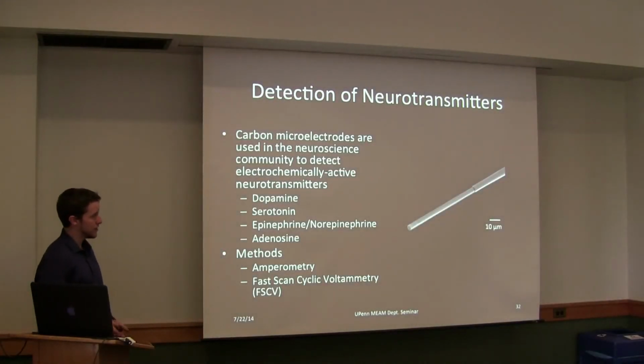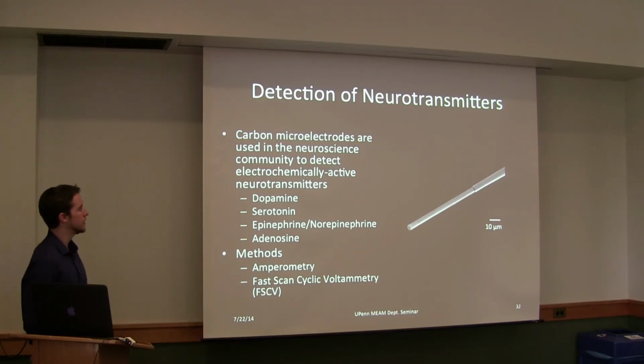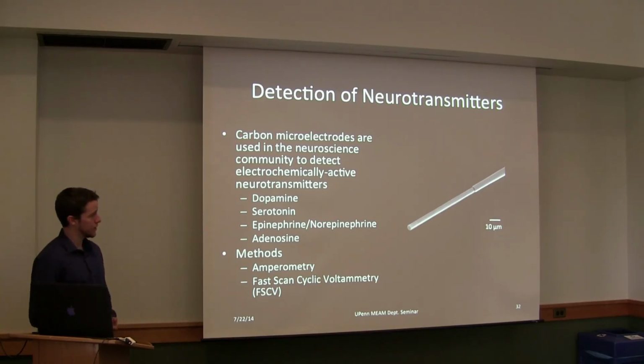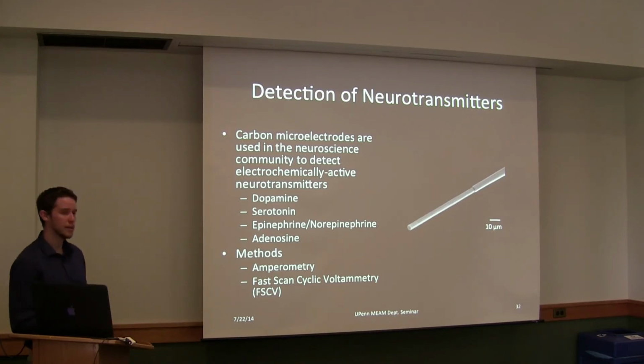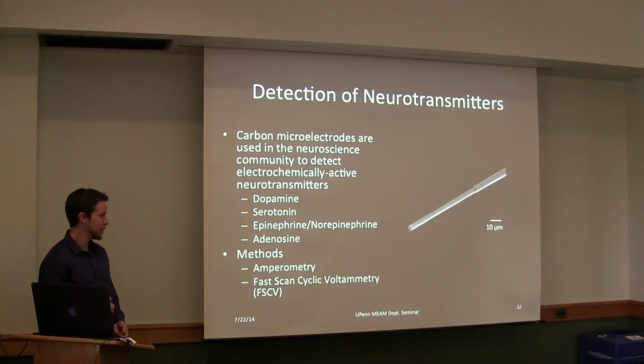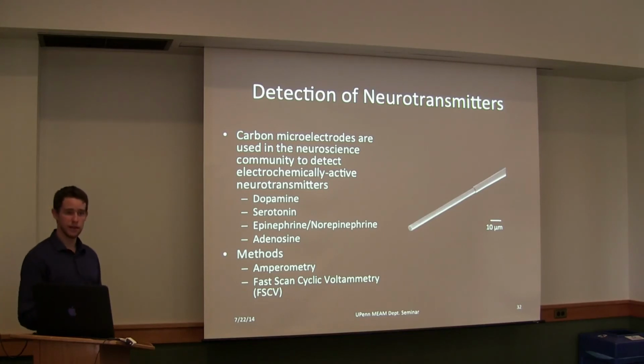And one application of cyclic voltammetry with CNPs comes back to detection of neurotransmitters. So we were looking through a catalog and found that carbon electrodes are commercially available, so we got interested in what they're used for. And it turns out that a lot of people use them for electrochemically detecting neurotransmitters, such as dopamine, serotonin, epinephrine, norepinephrine, adenosine. I think octopamine is also redox active. And they use methods, specifically amperometry, where they hold the electrode at a fixed potential and measure peaks in the current, or spikes in the current due to the presence of these neurotransmitters.